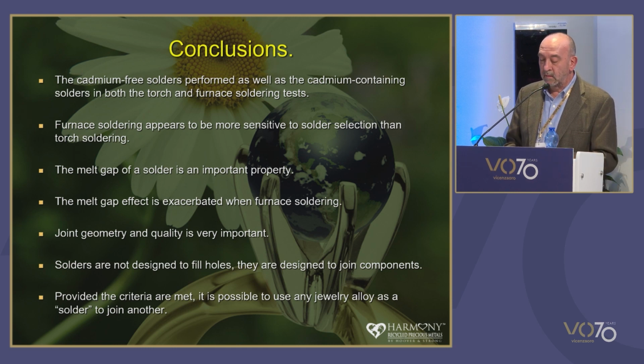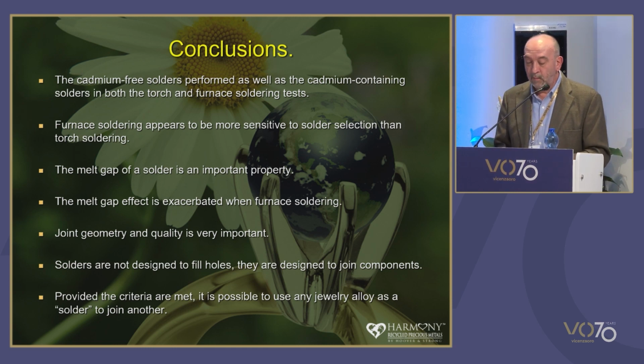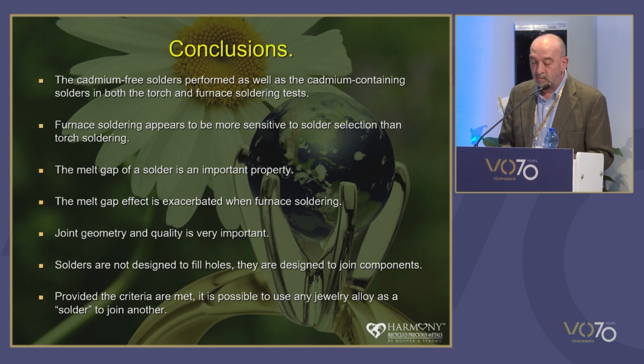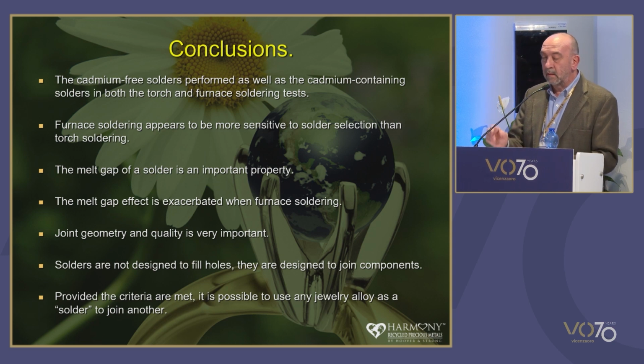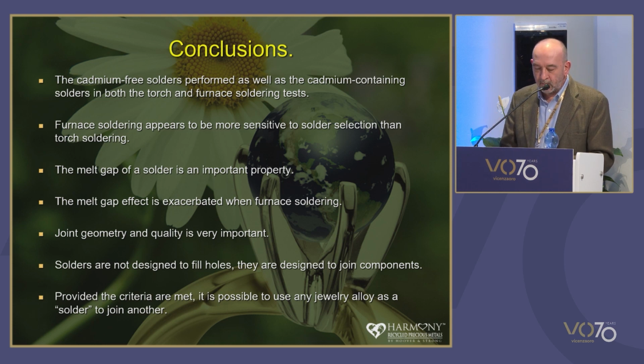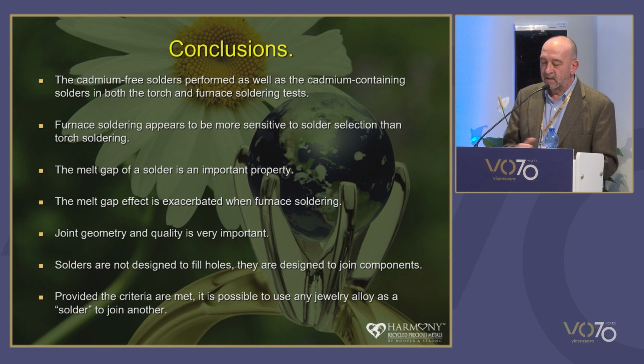The melt gap of the solder is an important property. A broad melt gap can decrease performance, and this is important because this is some of the information that's available to the purchaser. And the melt gap effect appears to be exacerbated when you furnace solder. Low melting point volatiles can be lost, and the change in melting temperature of the residual solder can potentially be raised above that you set on your furnace.